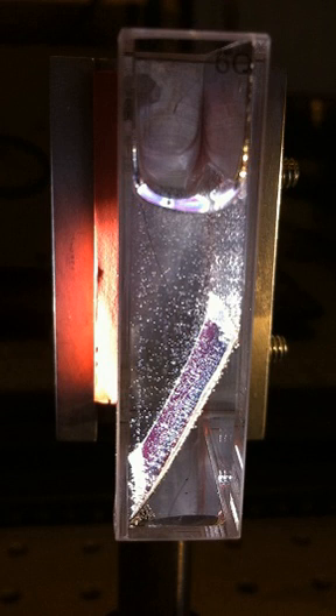Bio-inspired manganese clusters have been shown to possess water oxidation activity when adsorbed on clays together with ruthenium photosensitizers, although with low turnover numbers. As mentioned above, some ruthenium complexes are able to oxidize water under solar light irradiation. Although their photostability is still an issue, many can be reactivated by a simple adjustment of the conditions in which they work. Improvement of catalyst stability has been tried resorting to polyoxometallates, in particular ruthenium-based ones.